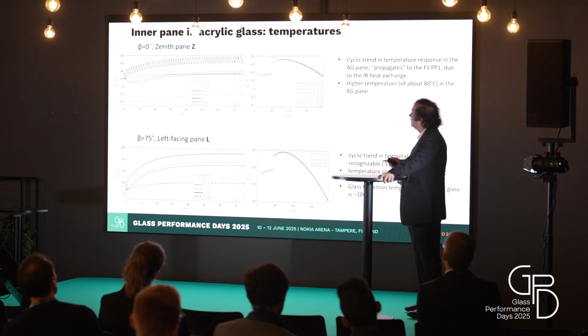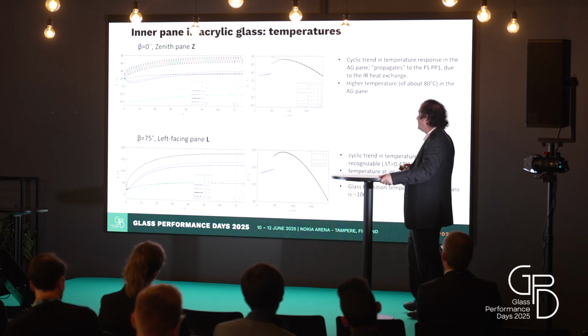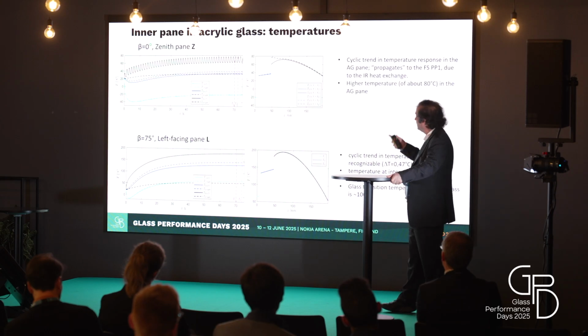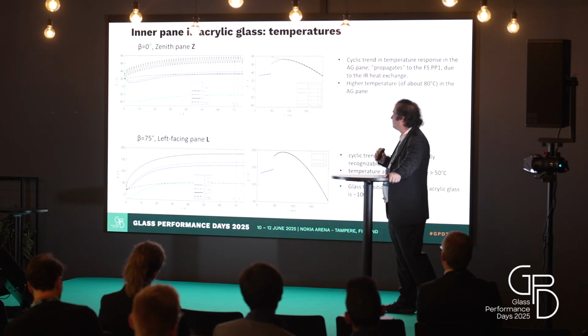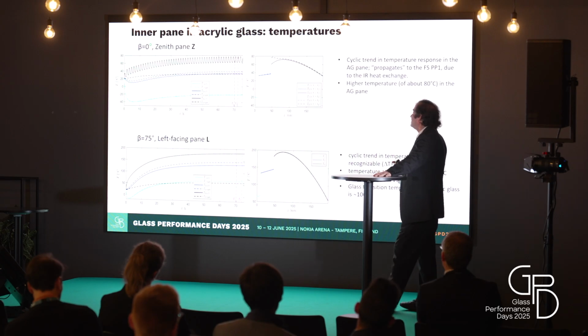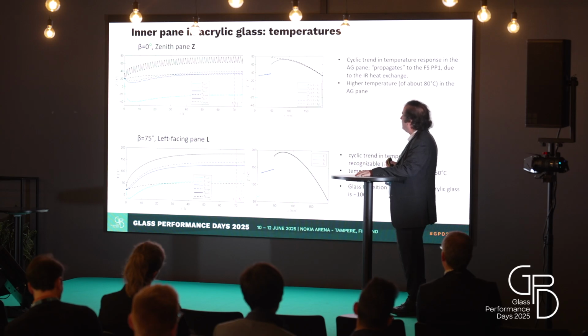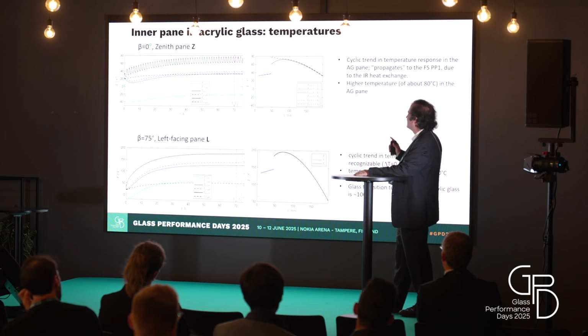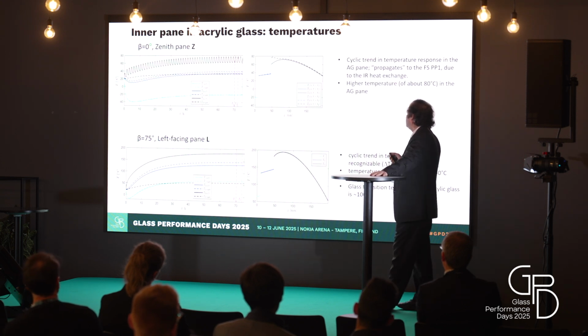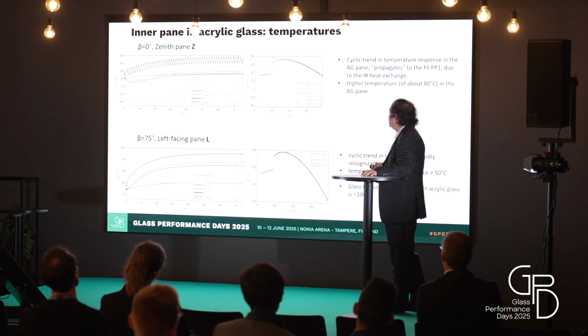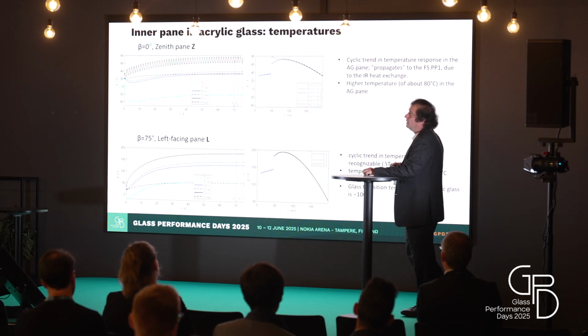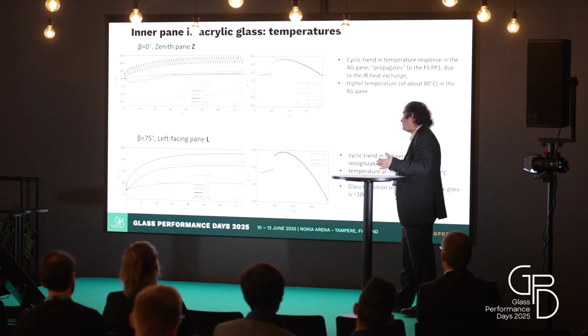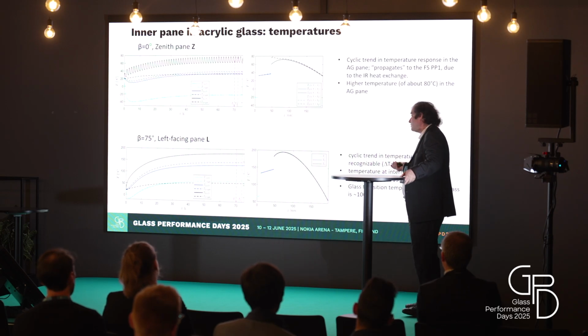And for the temperature, you can see that now the period of 90 minutes of revolution comes into play, because you can see this wavy response. An important thing is that there are conditions, in particular the angle beta of the orbit with respect to the sun rays, 75 for a left-facing pane. In theory, you could reach almost 100 degrees in the acrylic glass pane. And this means that, of course, you are close to the glass transition temperature, so you cannot use it anymore.